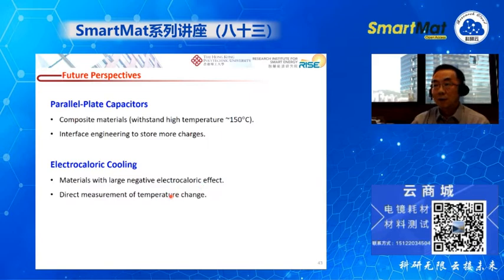And for an efficient cooling device, we wish to have both materials. Okay, so nowadays we can only find quite a few materials having the negative electrocaloric effect. So it is still quite challenging to find materials with a large negative electrocaloric effect. And also, many of the measurements of the temperature change are not direct, but indirect. So we need to find some accurate direct measurement for the temperature change when we apply or remove the electric